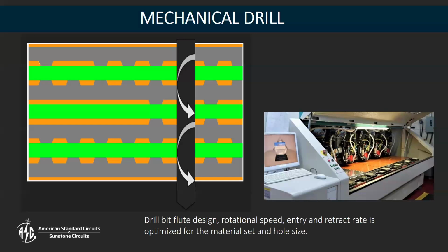So the panels go over to the drill department, and they do a test on some coupons, usually some registration coupons, to ensure that the drilled holes are hitting all of the internal layers like we'd expect before we actually drill the images. Once we verify that the registration to those internal layers is good, we drill the panels there.